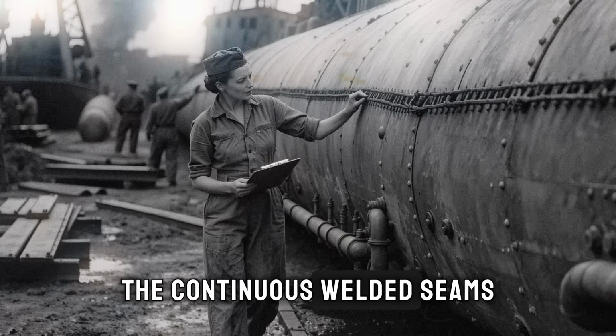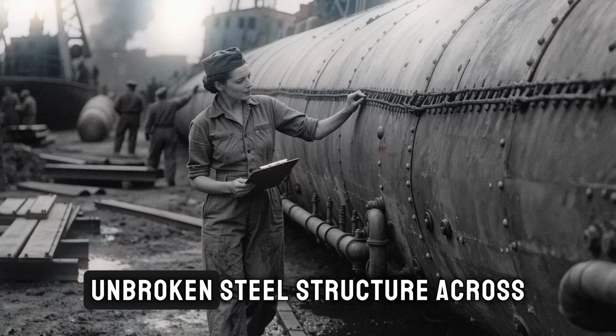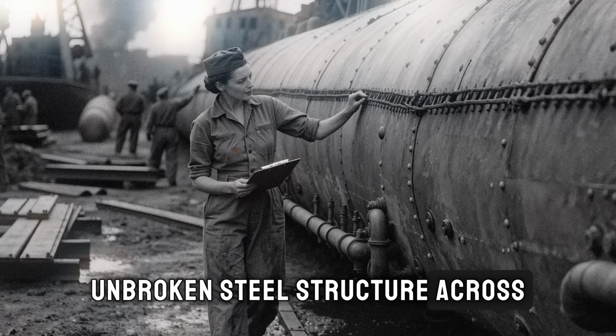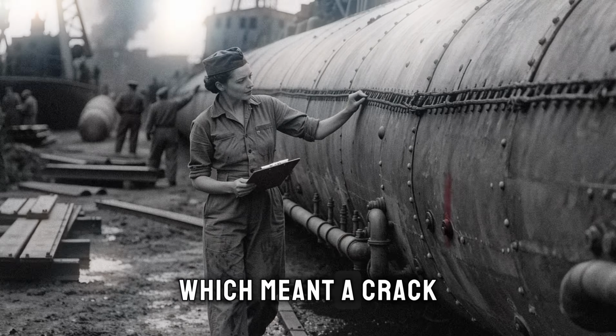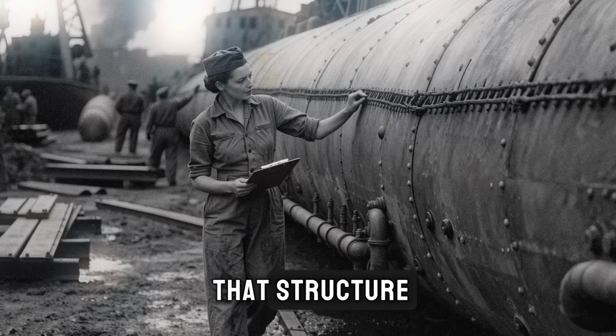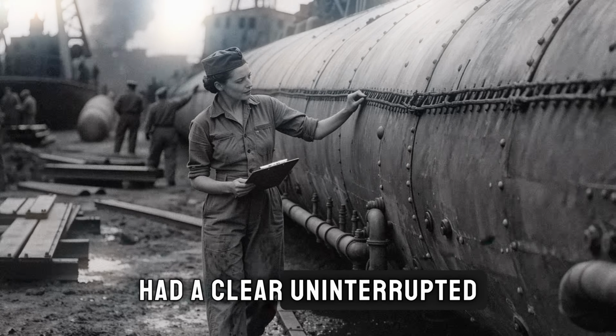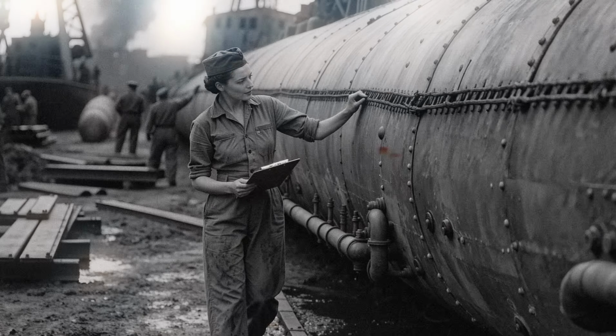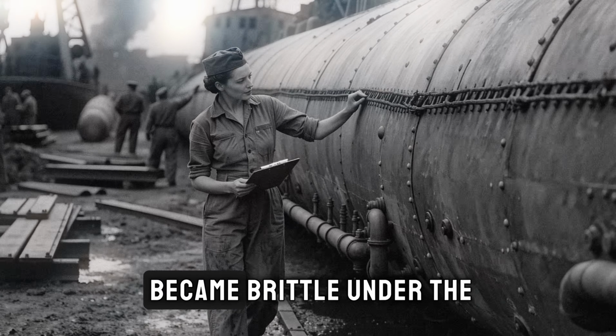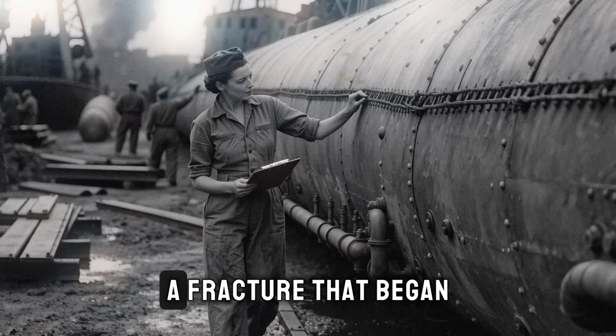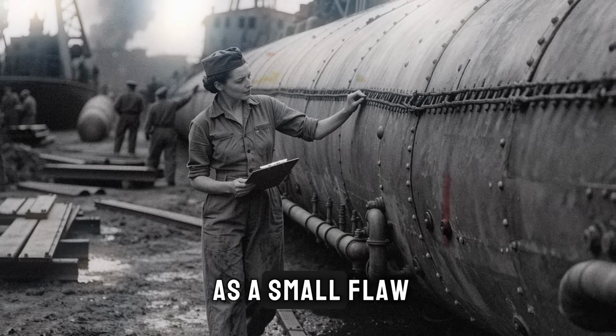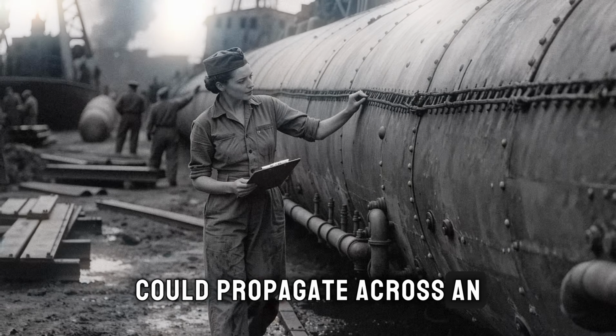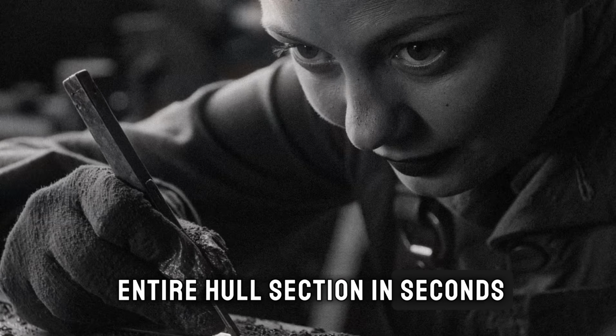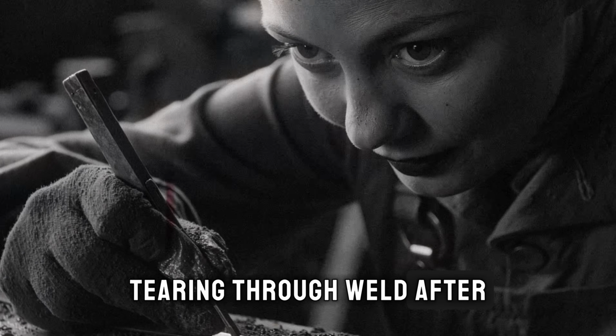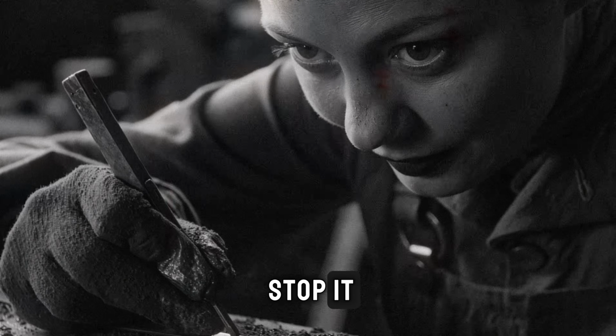The continuous welded seams created a single, unbroken steel structure across the entire ship, which meant a crack that started anywhere in that structure had a clear, uninterrupted path to travel. If the steel itself became brittle under the right conditions, a fracture that began as a small flaw could propagate across an entire hull section in seconds, tearing through weld after weld with nothing to stop it.